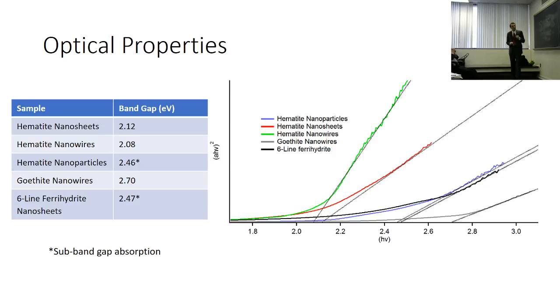It actually, the spectrum looked very similar to the hydroxide precursor, and it had a lot of what you call sub-band gap absorption, where it shouldn't be absorbing below the band gap. It's weird, if you cut it over here and don't look at this part, but look at this part of the nanoparticles, you'll get a very similar band gap. So the thought maybe is, maybe you have two materials here, hydroxide and an oxide, and the hydroxide is coming from these hydroxyl groups on the surface.